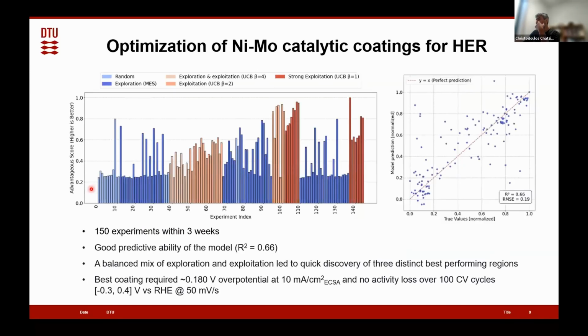Here's the evolution of the combined advantageous score of each coating as a function of experiment. We carried out 150 experiments, which required less than 3 weeks' time to be completed. Here you see the ability of the algorithm used to predict the actual experimental values measured. With an R-square of 0.66, fairly good predictive ability.